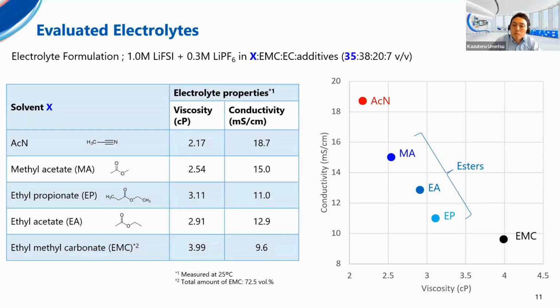So in this test, 35 metric percent of acetonitrile and three kinds of esters were used: methyl acetate (MA), ethyl propionate (EP), and ethyl acetate (EA). And ethyl methyl carbonate (EMC) was used as a control. The electrolyte consists of 1 molar of lithium FSI and 0.3 molar of LiPF6 in EMC and EC solvents with 7 metric percent of additives. Their viscosity and ionic conductivity were measured at 25 degrees C, and the results are shown on the right side of the table.